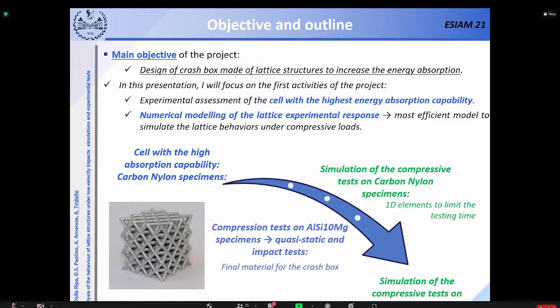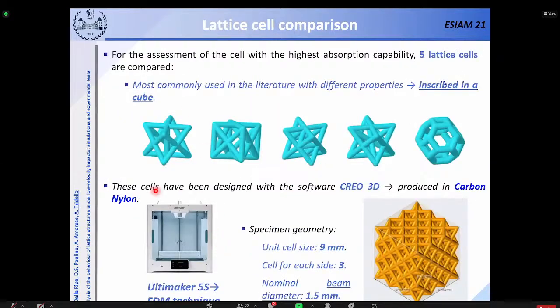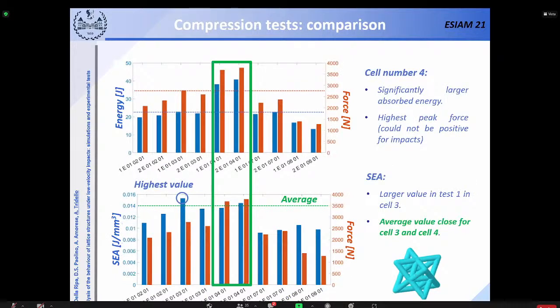The first validation and numerical prediction was performed with carbon nylon material produced with this Ultimaker manufacturing equipment, and then we ran quasi-static compression tests and also numerical models, and we got that the best choice for the lattice cell was the lattice cell number 4.